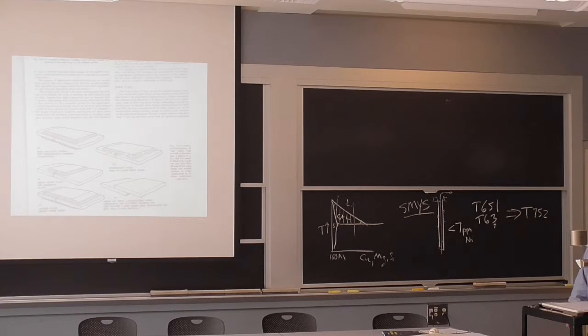So out of how many specimens? 4,290 tensile tests. 40% of them had a very narrow distribution of yield strengths. But then, this is actually, this is all 4,000. But 180 specimens from a single sheet had a narrower distribution. But whether it's steel or aluminum or any other metal, you're going to have a range of properties. And we usually design for specified minimum yield strength, SMYS. So the designers are going to specify, they're going to design assuming they got the worst, worst piece of material there. And that's sort of what happened with the Seawolf. I told you the Seawolf, they thought they were welding HY100. They thought they had a filler wire that would be an HY100 filler wire. But because of the range of variability, they actually got something more like an HY130 filler wire. They needed tighter hydrogen control. They didn't have that. And they welded up 18% of the ship with a filler wire that was a little too rich in composition.